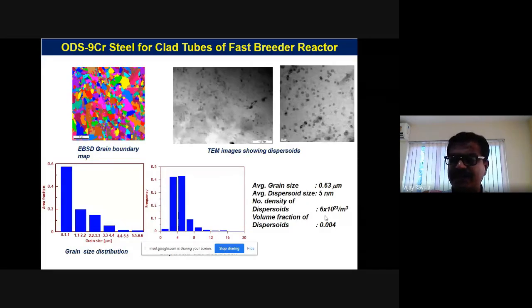Because what happens is, if you increase the volume fraction, the material will become brittle. It becomes like a ceramic. So the ductility comes down. So that's why we need to have an optimum content of these oxide particles. So the finer the particles, the more the number, and you can get it with a lower volume fraction. That's what we were able to achieve.